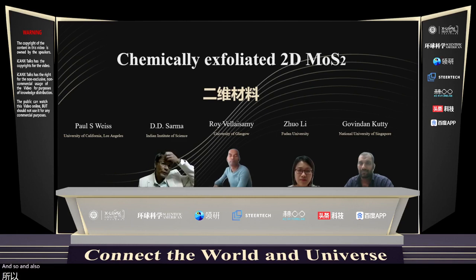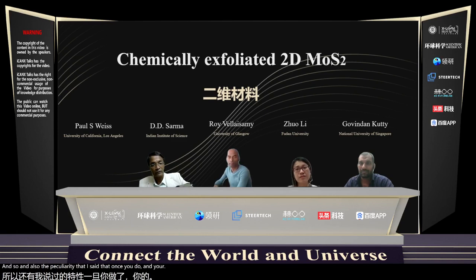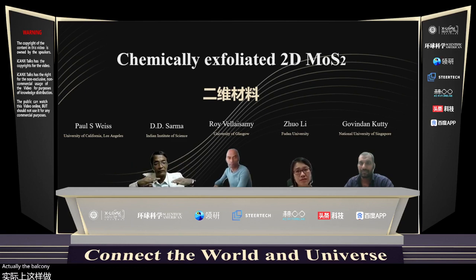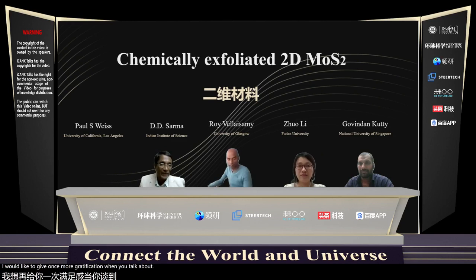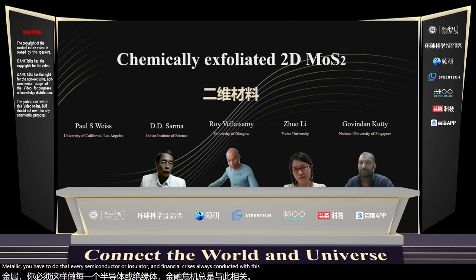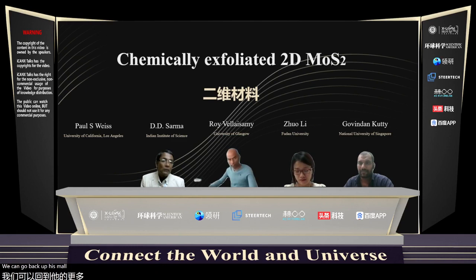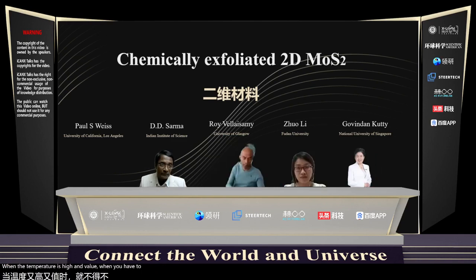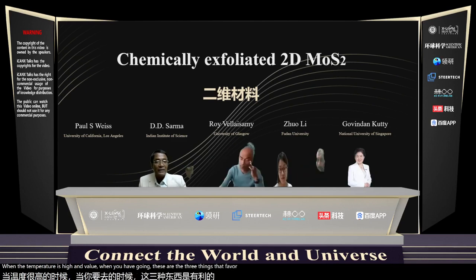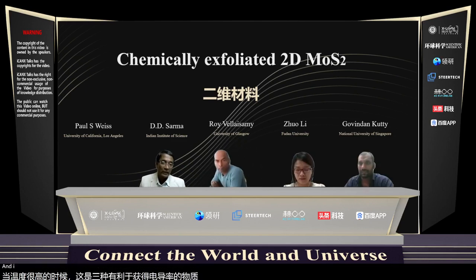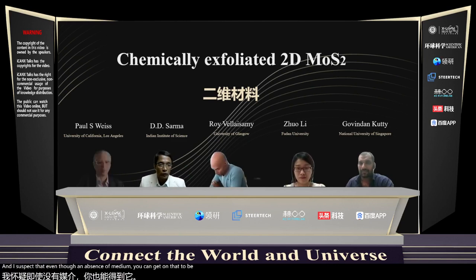And also the peculiarity that I said, that once you have a sulfur vacancy, the vacancy level drops down and you dope into that level. So your conductivity would go up. I would like to give one small clarification. Every semiconductor or insulator at a finite temperature is always conducting, because there's some electron-hole excitation. The question is, when the band gap is small, when the temperature is high, and when you have doping, these are the 3 things that favor getting conductivity. And I suspect that even in absence of lithium, you can get conductivity because of sulfur vacancies. And this, I'm sure, has been talked about in the literature.